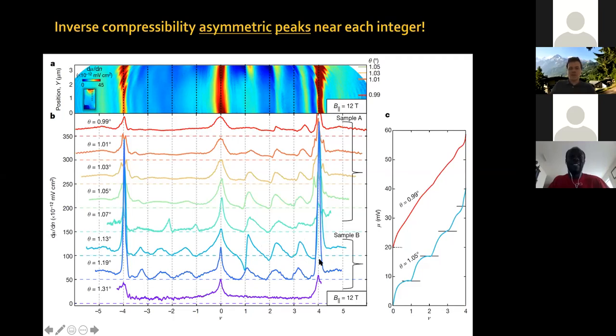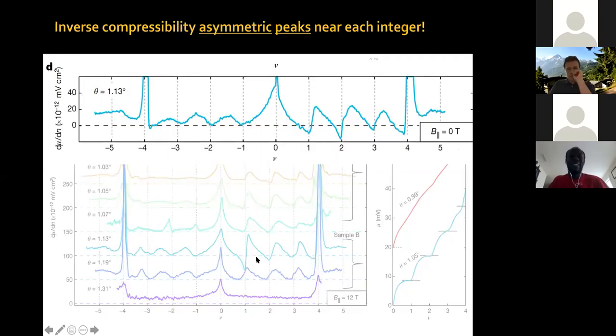Now, the other thing that I want to tell you about is you can integrate these curves. Of course, you can see that for 0.99 degrees your chemical potential has this square root density dependence, but relatively few features until you reach the step at filling factor 4. However, for the 1.05 degree samples, you can see this square root, then another square root, then kind of another step, etc.